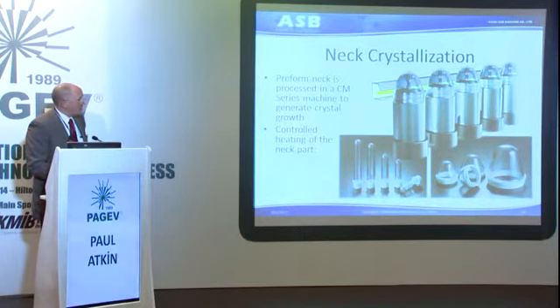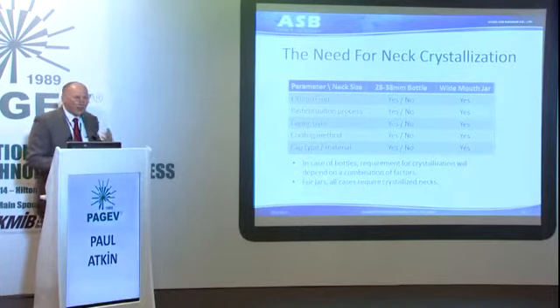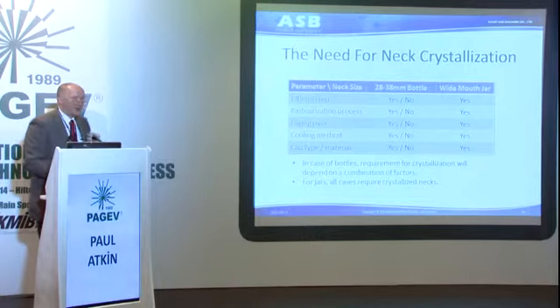If neck crystallization is necessary, the preform is passed to what we call a CM series machine, where just the neck part is heated, and the result will be preforms that look like this. Now, as I said, the need for crystallization in the neck is variable. If we're talking about bottles, then there are several factors which will dictate whether the neck can be amorphous or needs to be crystallized. However, for jars, we always say yes, we need to have the crystallized neck because the size would be too difficult to manage against distortion.